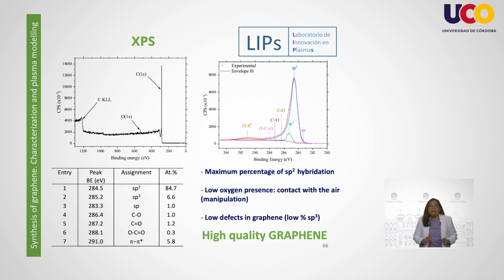In this slide, we can observe the XPS analysis, which was explained in the second block, as an analytical technique to analyze the element composition of the sample. For our graphene produced by plasma with the Tiago torch, we can observe the presence of carbon atoms as the majority element and a very small amount of oxygen that can be mainly attributed to the influence of atmospheric oxygen during the extraction of graphene from the reactor. And the deconvolution of the carbon 1s peak allows a detailed analysis of the types of carbon present on the surface of graphene, confirming a maximum percentage of sp2 hybrids and low defects in graphene corresponding to sp3.